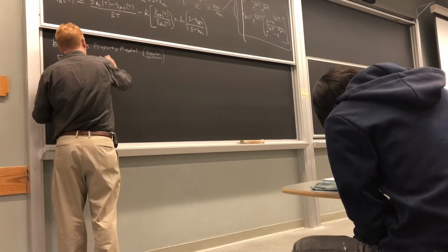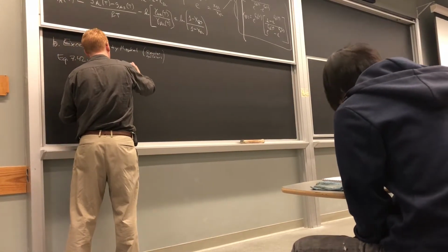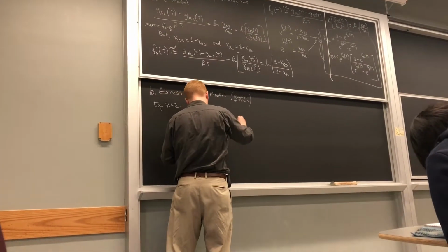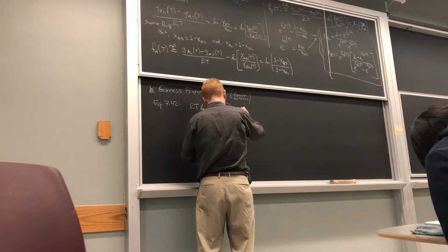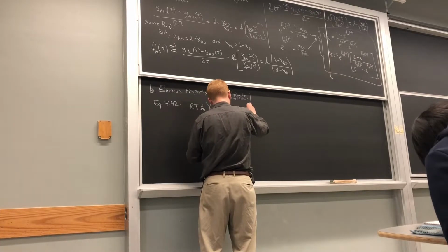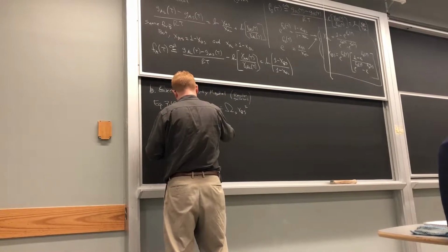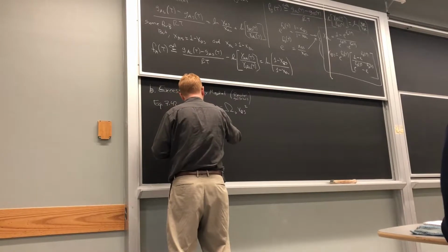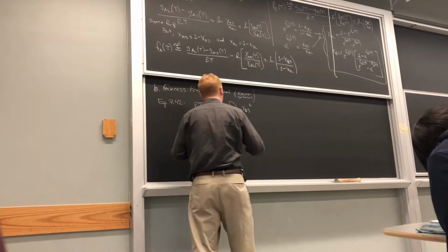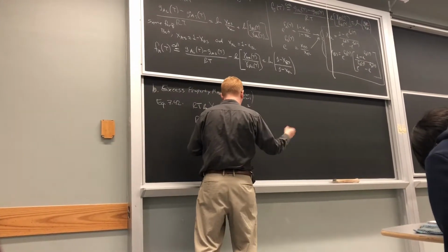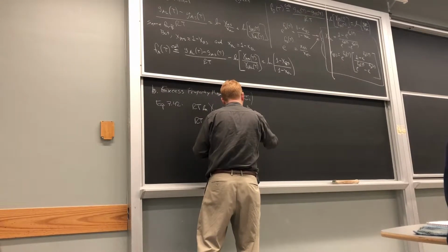So we've got RT natural log of gamma AS is equal to the omega for the solid, XBS squared, and we have the same sort of thing for the liquid, but we have a different omega for the liquid because maybe the interactions are different in the liquid phase, so we just account for that.